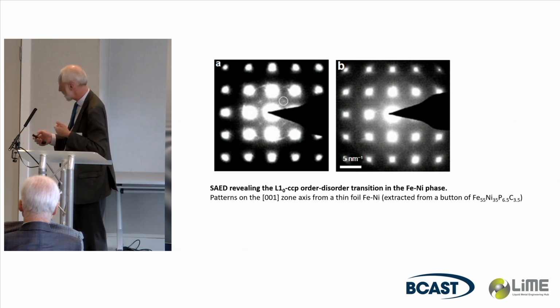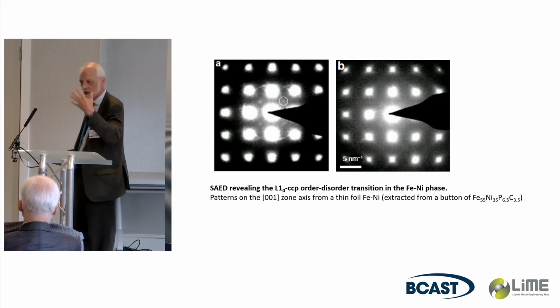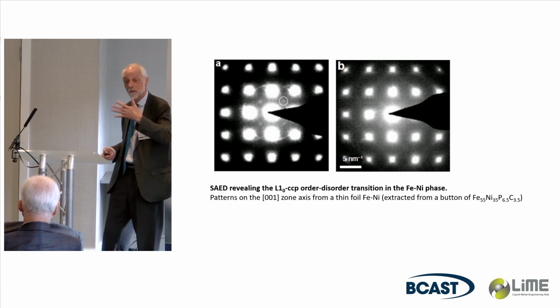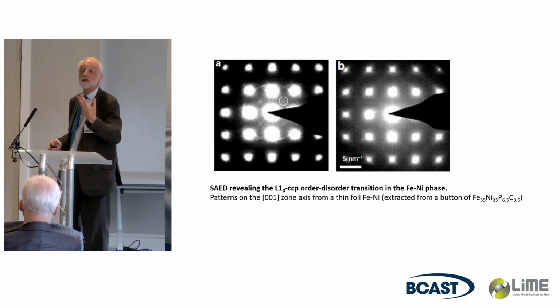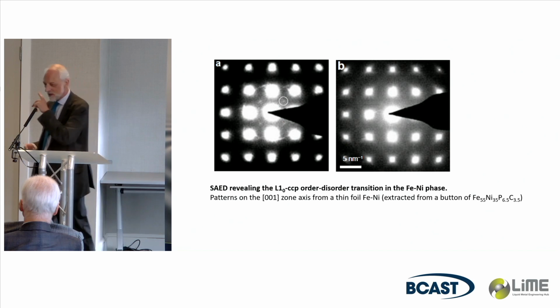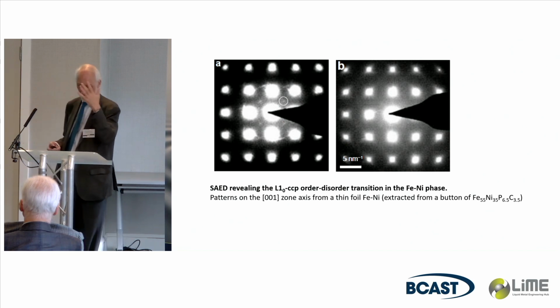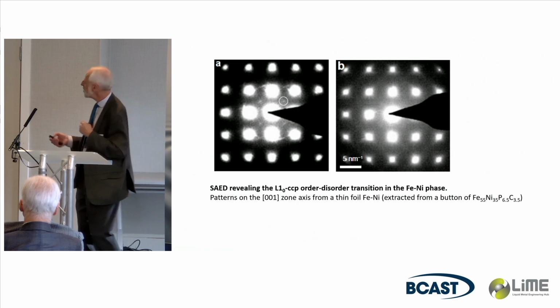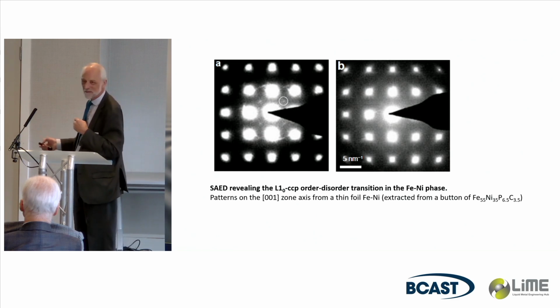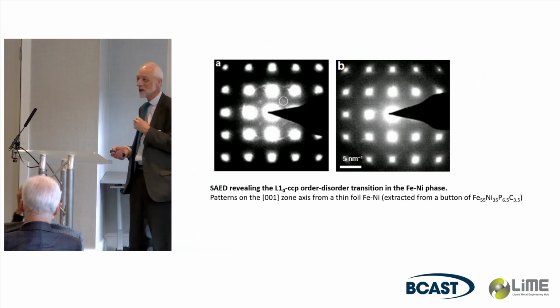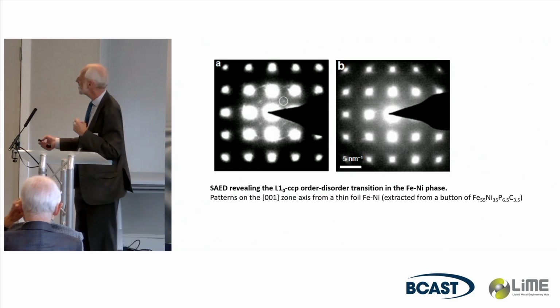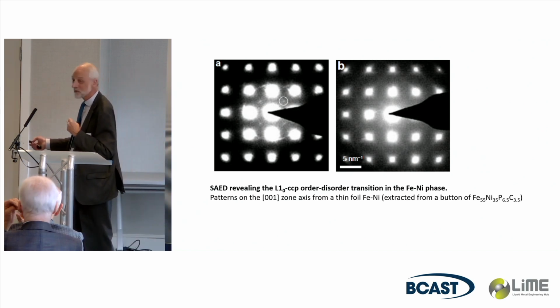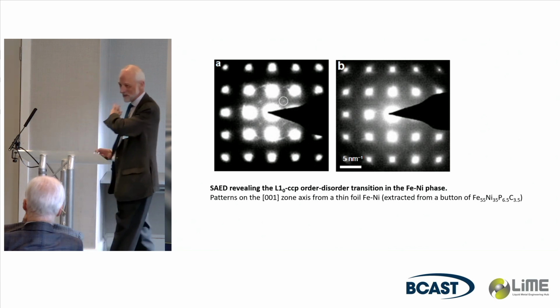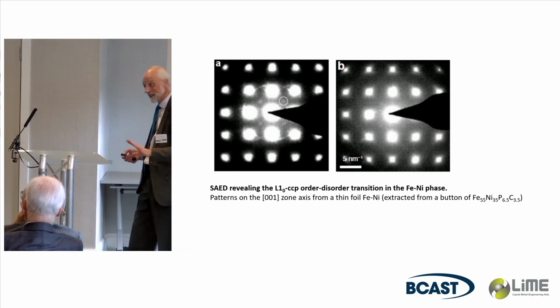Well, you can see that we have a ring here, which will be some sort of deposit on the thin foil prepared for TEM. So it's a redeposition. So we went to some effort to eliminate that by cleaning up the thin foil preparation. When you clean that up, you don't get these peaks. So we come to the reluctant conclusion, having looked at it closely, that these are actually a rather weird double diffraction from the deposited nanocrystalline rings.